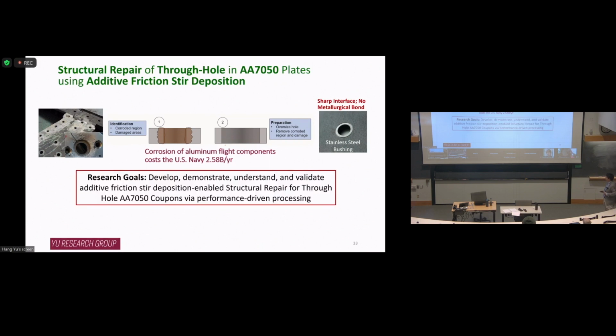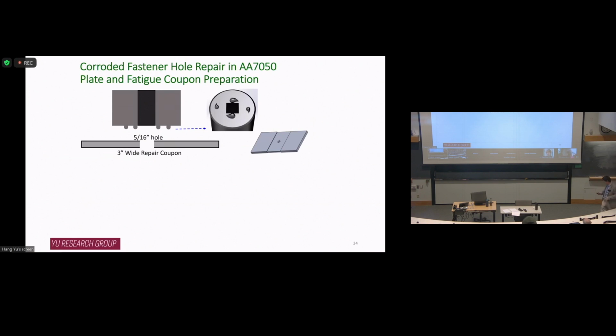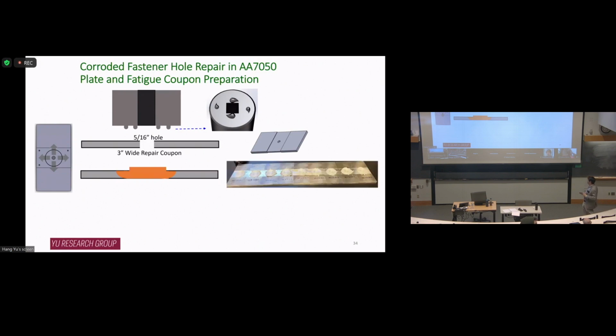This project is based on the idea that now we can fully fill holes, so maybe we can apply that to address this problem. If we can be successful, we can shorten lead time, reduce the cost, and possibly repair this multiple times. Here is a quick illustration of what we did. We started with a larger hole after we removed the corroded material, and then we fully filled the hole using additive friction stir deposition. We need to develop a deposition processing recipe and deposition path to fully fill the hole and make sure there's no defect or kissing bond. Then we can remove the excess material and re-drill the original hole size.